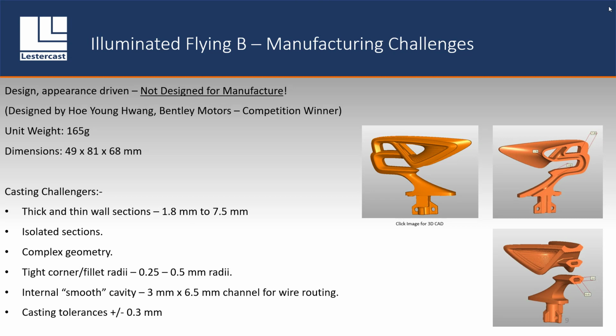Unit weight is only 165 grams, and dimensions are relatively small, 49 by 81 by 68 millimeters. So, casting challenges: thick and thin wall sections. We try to set a nominal no less than 1.8 millimeters, but we had some heavier sections, a few still in existence, up to 7.5 millimeters. Isolated sections within complex geometry, tight corner and fillet radii down to 0.25 of a millimeter to half a millimeter radius. Yeah, it doesn't help us within our casting process.